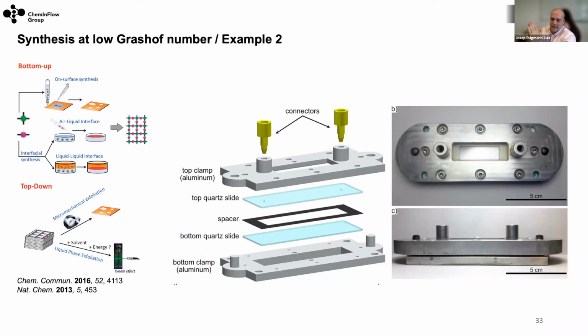As you probably know, a place where you also have a low Grashof number is the International Space Station. There, the Grashof number is very low, and this has proved to be an ideal condition, for instance, to grow ZBLAN. It is a glass that is supposed to have much richer qualities than silica, for instance for optics, and it would be great to have single crystals of it. But what happens is that on Earth, with the normal gravity that we have, it's not possible to achieve single crystals. There are many grain boundaries that then reduce a lot the good properties that it has.